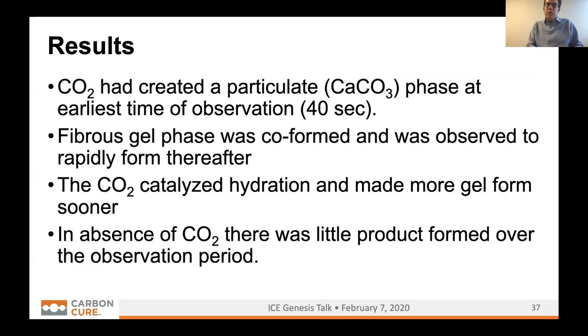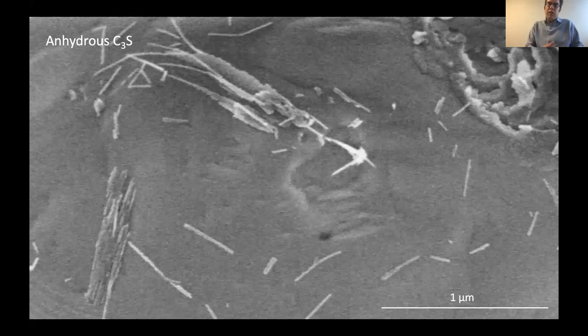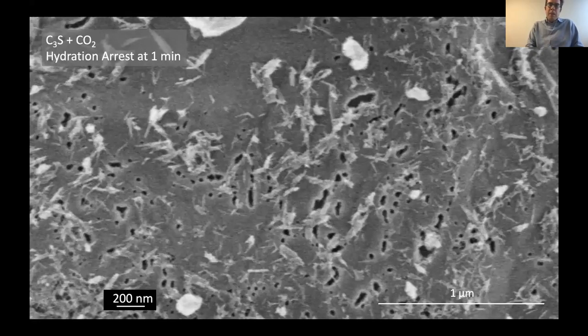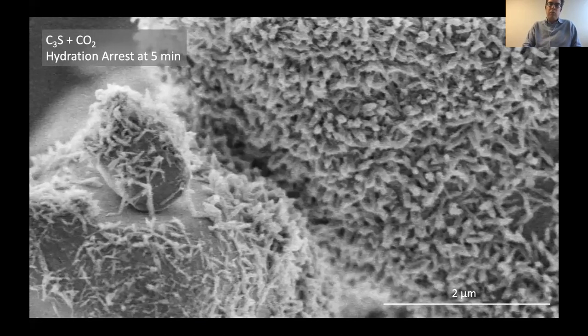What we're seeing, in addition to particulate calcium carbonate, is a fibrous gel phase. So this is impacting the chemistry to form additional calcium silicate hydrate more than with the control case at the same time. So if we just look at what that looks like under a microscope, this is the anhydrous tricalcium silicate. So before the water is added, this is the case where we've added CO2 and arrested the hydration at 1 minute. And you can find, if you were able to zoom in on these particulates, you would find these are where the CO2 has ended up in carbonates. And you do not see these small particulates in the unhydrated case or the default case.